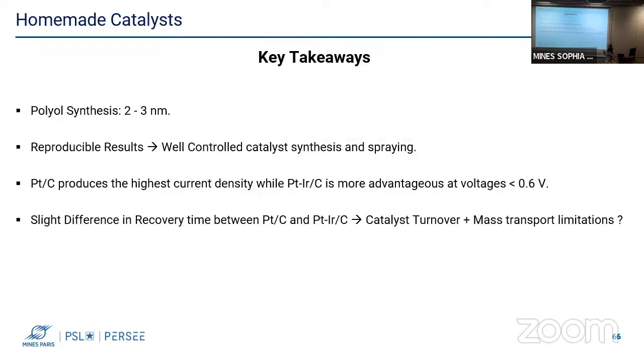At the end of this study, we could say that the polyol synthesis succeeded in preparing catalysts in the desired size range. The results for all the catalysts were reproducible, which means that the catalyst synthesis and the spraying process were well controlled. Platinum on carbon produced the highest current densities, while platinum iridium on carbon was more advantageous in the low potential region. And there's a slight difference in the recovery time between platinum and platinum iridium on carbon, which means that this could be a matter of turnover in addition to mass transport limitations.